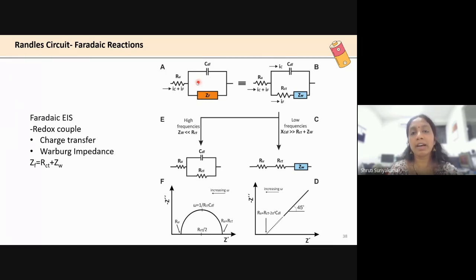So, for example, this is going to be the initial case. I have an uncompensated electrolyte resistance. I have a double layer capacitance. And then there was earlier a charge transfer resistance. Now, since mass transfer is also involved, I call this Faradaic impedance. And this Faradaic impedance will be given as charge transfer and Warburg. And this is what we get.